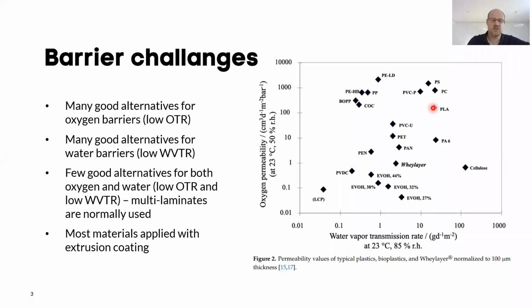If we look at the barrier challenge as such, we usually have either a quite good oxygen barrier or a quite good water vapor barrier. There are few exceptions where you have both. Polyethylene, for example, is an excellent water barrier, but a poor oxygen barrier. Cellulose is a good oxygen barrier, but it's quite water sensitive and not a good water barrier. It's the same with EVOH. There are two exceptions. One is PVDC, which shows quite good oxygen and water vapor transmission rates, and the other is liquid crystalline polymers, which also do. I think both of these have a high crystalline content, especially the LCP.